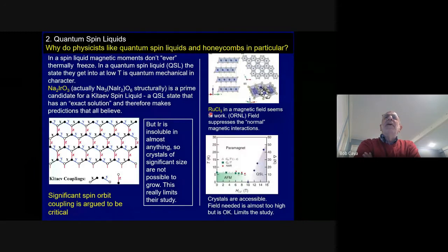We learned early in our careers that as you go to lighter and lighter elements, the effect of spin-orbit coupling is weaker. And in this theoretical model for honeycomb lattice, you have to have strong spin-orbit coupling. So what these people did was, instead of using a 5D element where the spin-orbit coupling was obviously going to be high, they used a 4D element where the spin-orbit coupling was not obviously high, and it worked anyway.